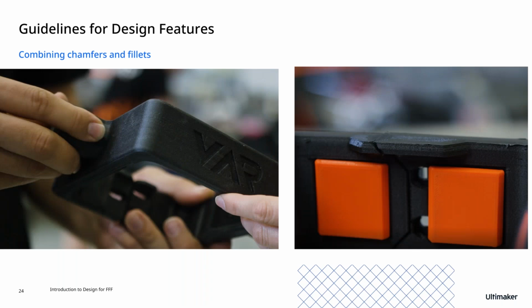The picture on the left is what we spoke about in terms of adding a chamfer and a fillet. This decreases the stress and improves the ergonomics and doesn't need support as well when printing it. The picture on the right shows you the empty slots, which were filled in with a bright red TPU print. Now, these are the points of contact with the metal piece and experience more wear. Hence, a wear-resistant material was used. Also, when this material eventually wears out, only these TPU parts have to be replaced instead of the entire 3D print. This is the modularity that we spoke about.